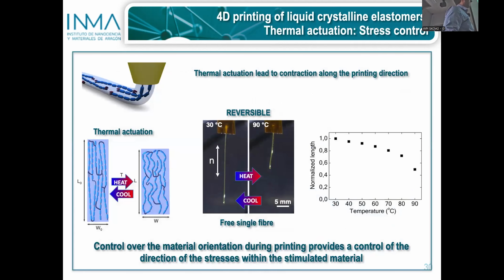Later we can release these fibers by using a sacrificial layer of polyvinyl alcohol. We remove the polyvinyl alcohol just by immersing it in water, a very simple process, and we get this straight fiber. When we heat it up, as expected, we get a fiber that is shorter, that contracts. And if you look carefully, you can see that it also has some expansion in the perpendicular direction. So this digital control that we have in the morphology is now translated into a digital control of the stresses we have in the printed material, in the liquid crystal elastomer.